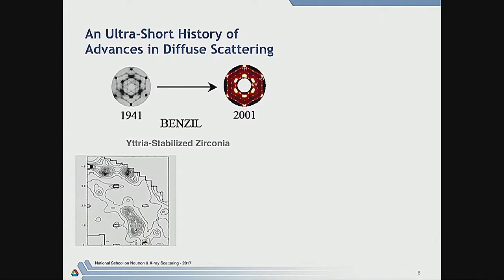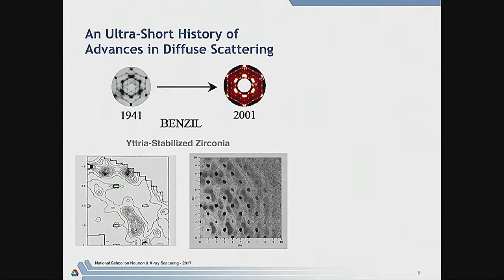So all we did was scan step by step at omega equals zero and raster through this, and got this diffuse scattering from yttrium-stabilized zirconia. It's the same material used to make artificial diamonds. And there's a lot of vacancy disorder in this material because of the different valence of the cations, which gives rise to this beautiful structure. That took 2 weeks. We measured it over Christmas break, came back and plotted it up.